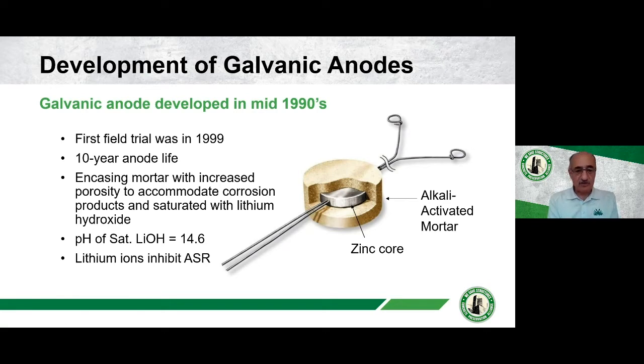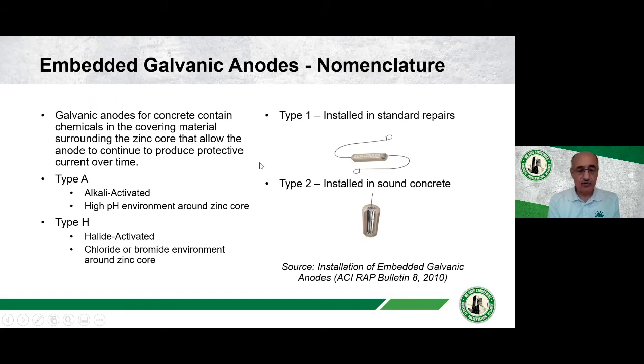After a few trials in the lab, we went out to do a field trial, on an actual structure, a bridge in Leicester in the UK, and this was in 1999. But before I go there, I just mentioned the types of anodes that actually exist and which one we were concentrating on at the time. There's a type A anode, which is alkali-activated. This is the one I'm talking about, and that was the prototype that I just explained. There's also a halide-activated zinc core that would normally be chloride or bromide.